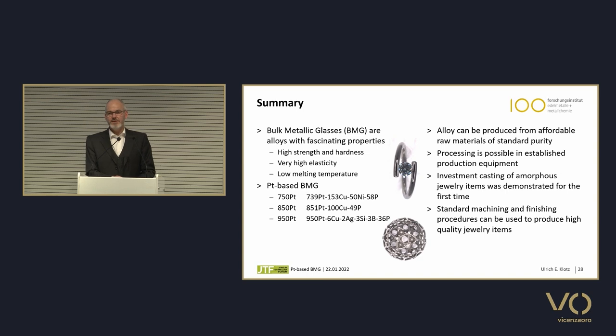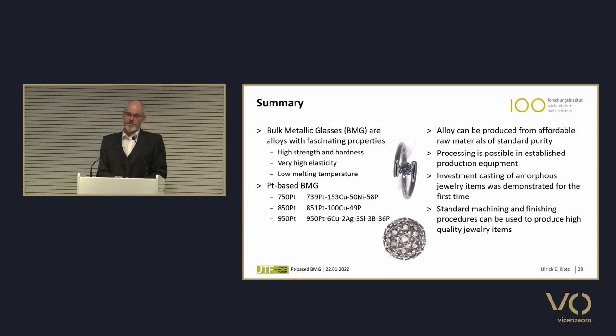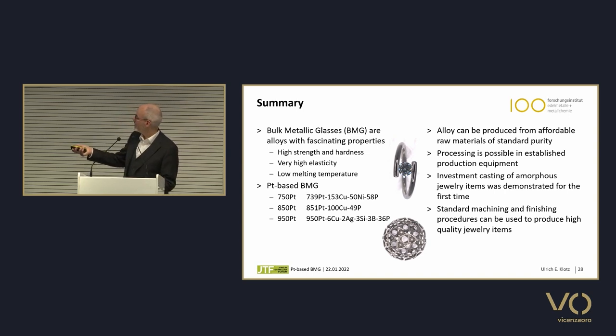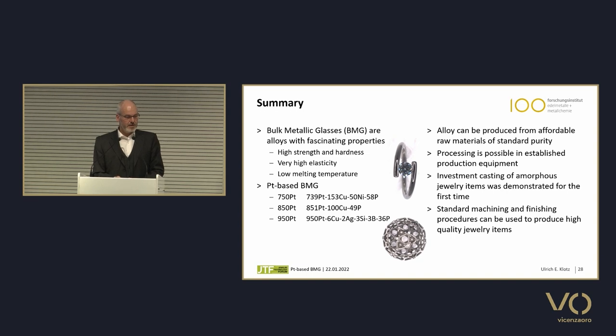Yeah, so this leads me to the summary. Bulk metallic glasses have fascinating properties. They are very highly elastic. They have high strength and hardness, very low melting temperature, which makes them perfect for casting. If you reach the sufficient cooling rate, which we did by investment casting with conventional investments, there are different alloy compositions that behave differently. The best glass former is the one with around 75% platinum. The higher the platinum content, the lower the glass forming ability is. After casting, it can be finished in standard techniques to produce really high quality surfaces.